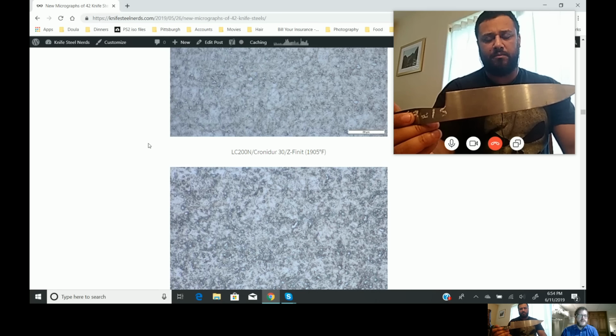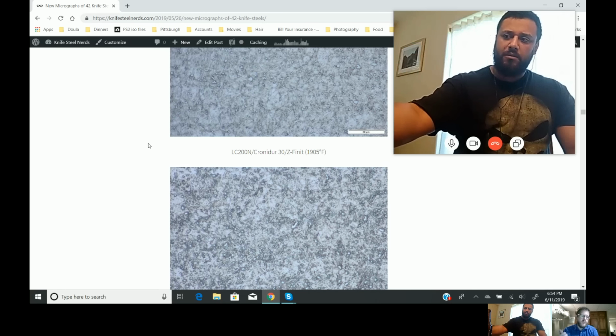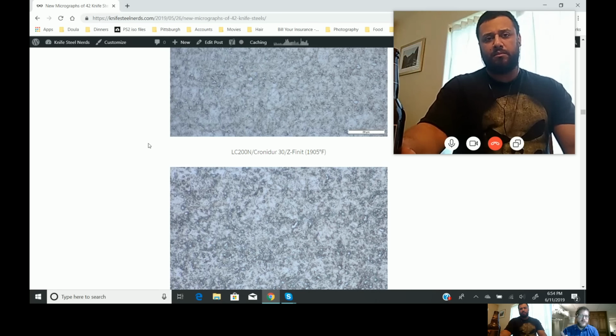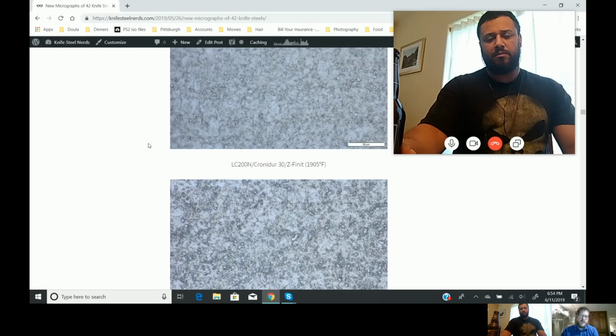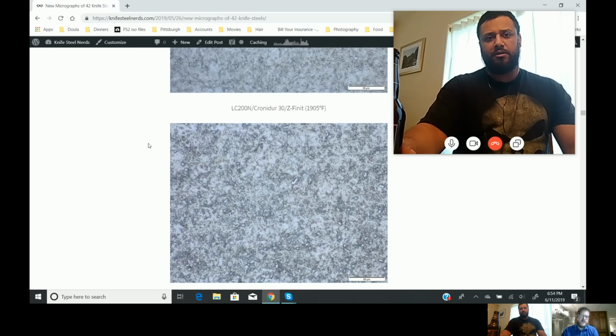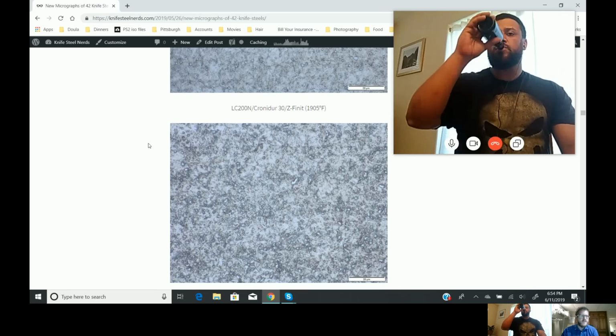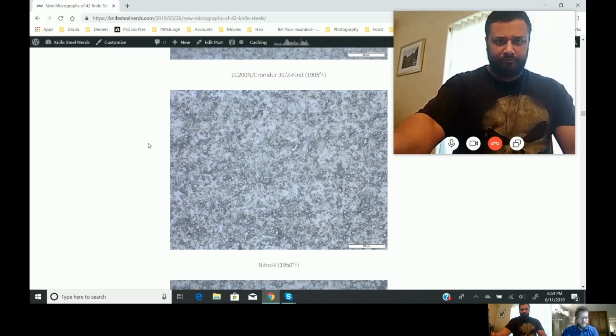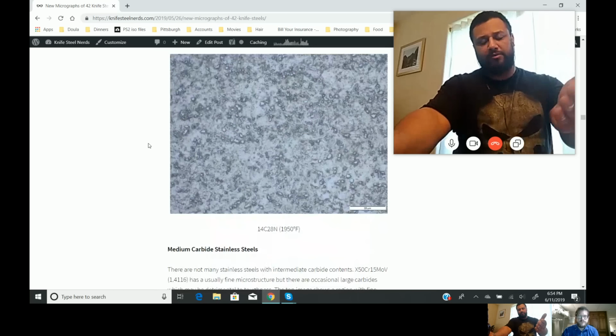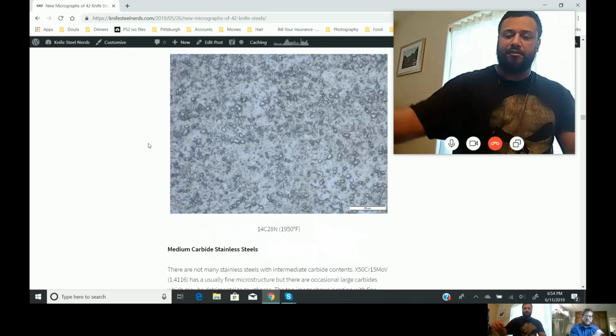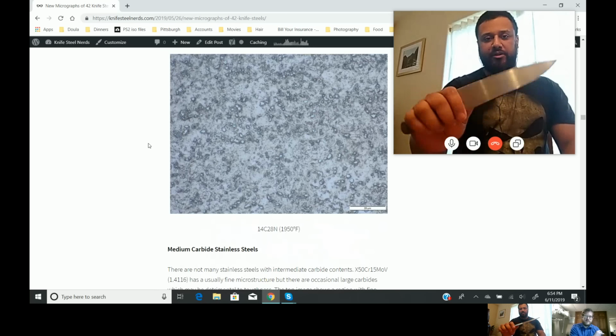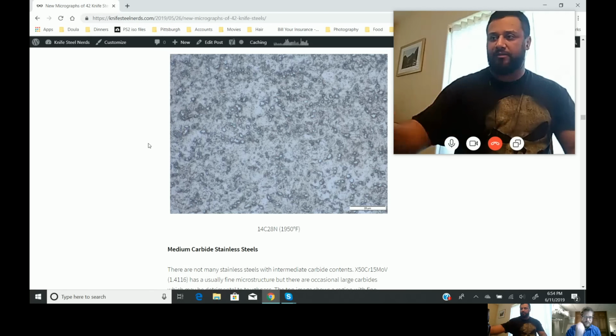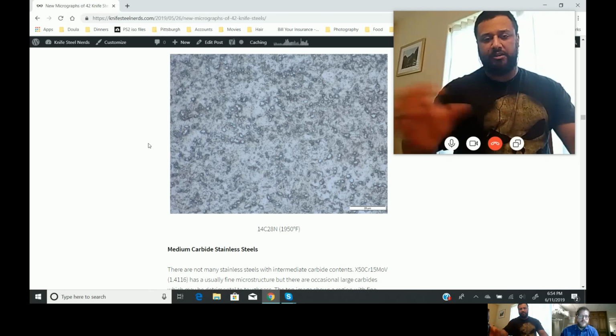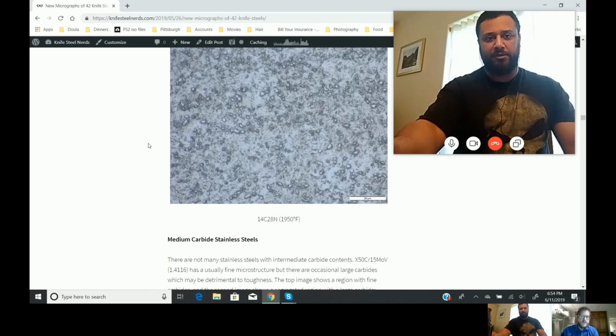So when you austenitize it at high temperature, the higher temperature you go, the more carbide is dissolving. And so there's going to be less carbide, and they're going to be a little bit smaller usually in the heat-treated condition. Though the first carbides that dissolve are the smallest ones, so it's a little bit complex. So that's essentially why we have the finer carbides with these AEBL type steels versus the CPM steel, which has more carbides. We're not able to dissolve all these. They're leftover primary carbides versus the AEBL, like secondary carbide. They're all precipitated out, so to speak, eh? Yep.